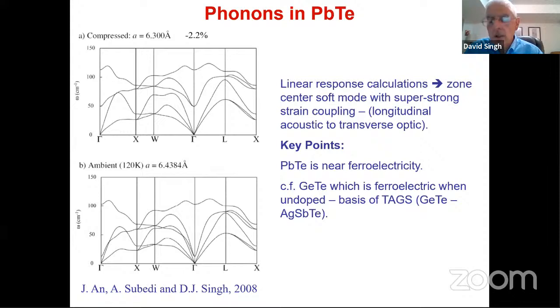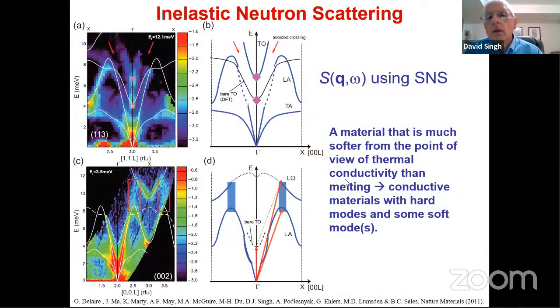That was the conclusion. So then our colleague did experiments with neutron scattering to see about that. And this is what he found. I'm not going to go through all this neutron data, but the point is what is seen is a very strong interaction between that ferroelectric mode and the acoustic modes that perhaps can explain the low thermal conductivity of lead telluride. There turns out to be some other factors as well, but it gives some of the explanation for the low thermal conductivity.